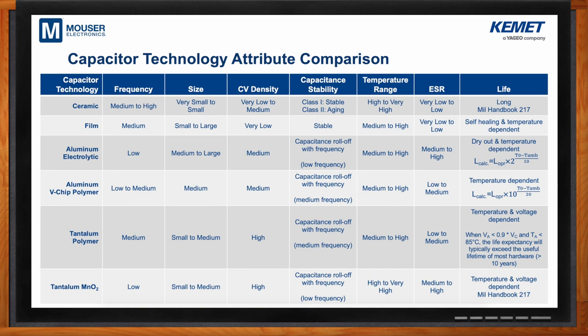The class twos, which would be barium titanate-based technology, have a much higher dielectric constant, but they have more negative attributes. One of them is DC bias. You put voltage on the part and it loses capacitance. It's just a characteristic of the barium titanate and the dipoles and domains within the barium titanate structure. There's also this oddball characteristic called aging. It doesn't mean it's getting old. It just means that it's losing capacitance over time because the crystalline structure of the barium titanate is changing from a cubic to a tetragonal structure and a dielectric constant. So that would be your ceramic technology.